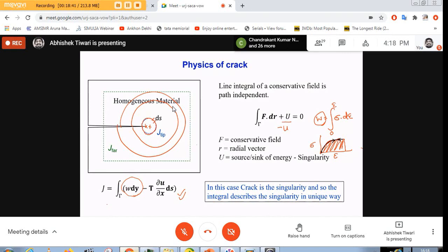But the reality is different. In reality, if I have a material and I'm loading it, this is usually for metallic material, this is the linear elastic part. If I unload anywhere in this region, it will obviously go back, but after that plasticity starts. If you unload it, then some amount of strain is recovered, which is elastic strain, and some amount of strain is not recovered, and that is plastic strain. So then it is not a conservative field.